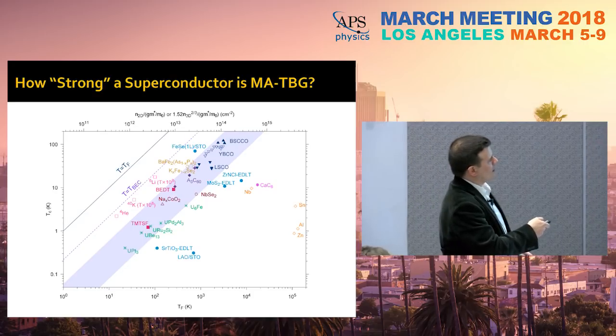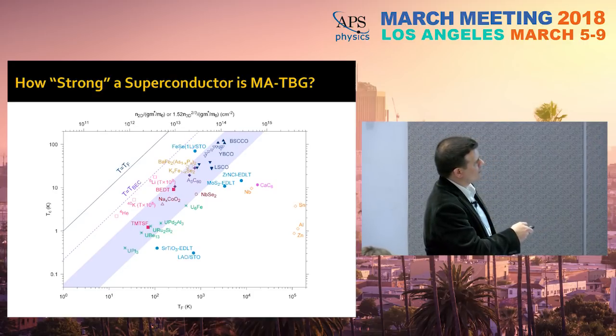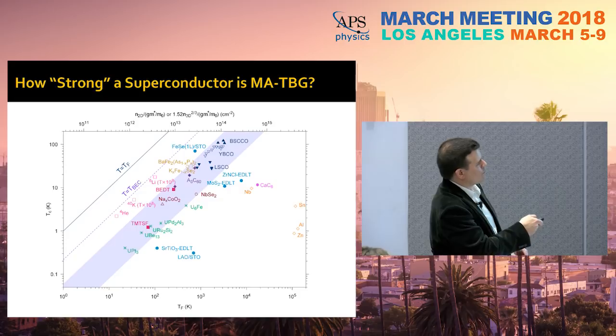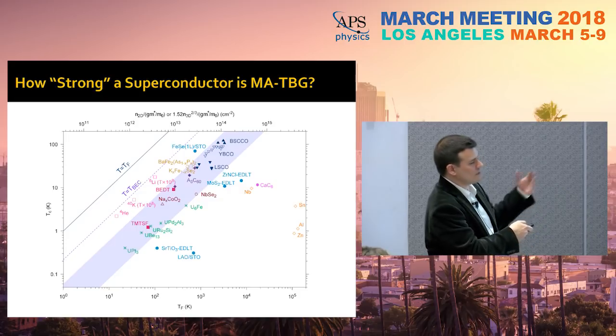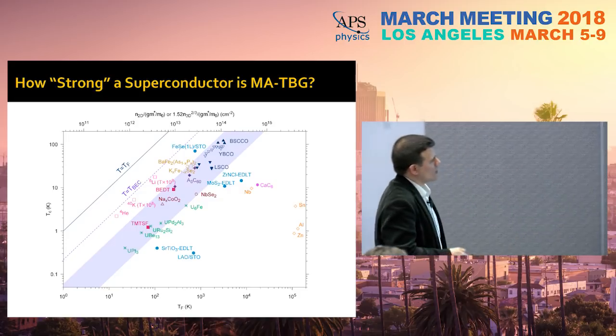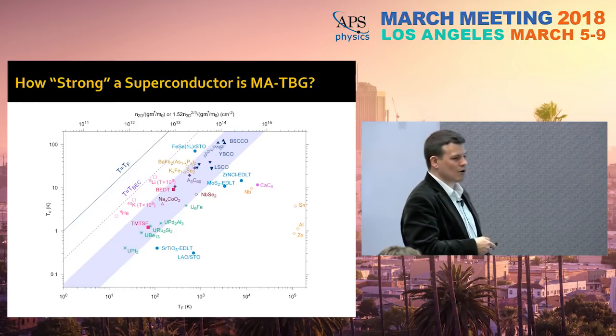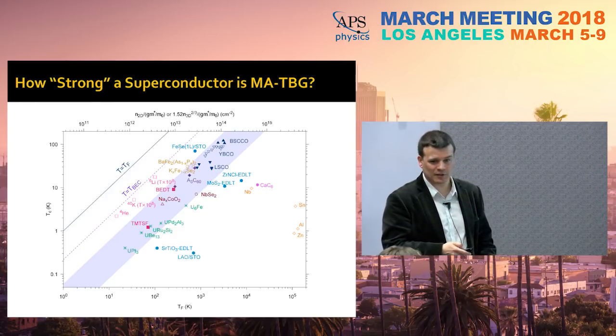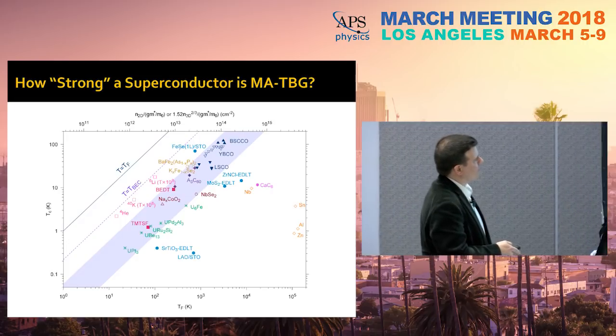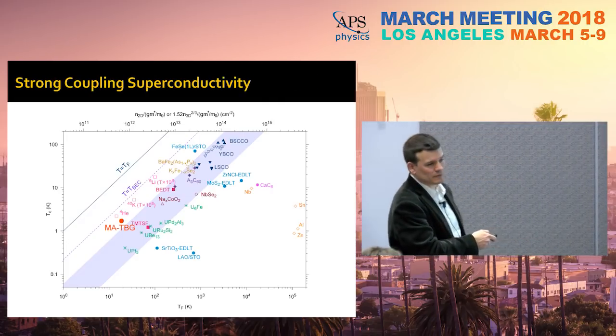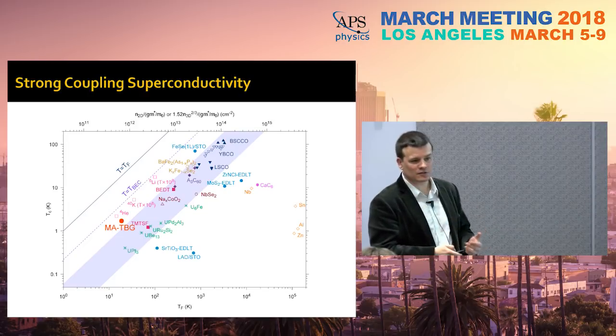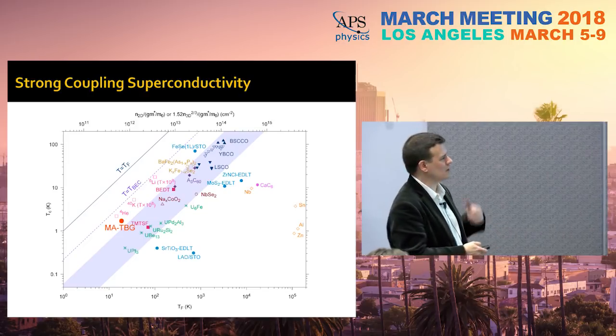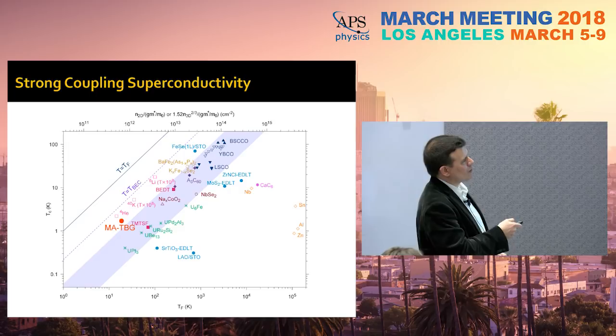These are data points for helium-4. This is for ultra-cold atoms, multiplied by 100 million on both axes, just so that they appear here, okay? They can reach very much this BEC-BCS crossover. So the stronger you go in this direction, the more unconventional typically, or the more exotic your superconductivity is. So magic angle twisted bilayer graphene happens to be there, okay? It is among the strongest superconductors that exist, in the strongest coupling. Only iron selenide monolayer on STO is a little bit higher.